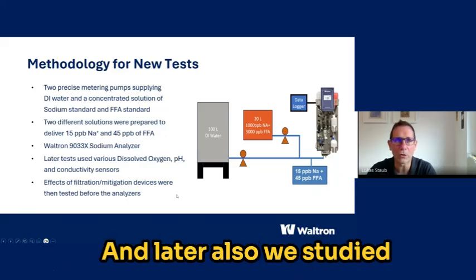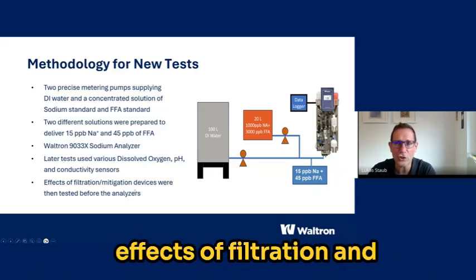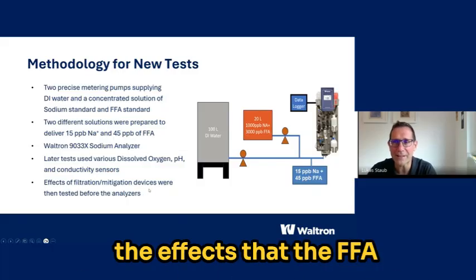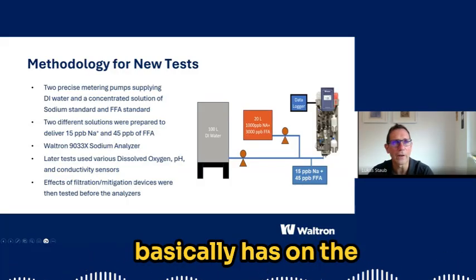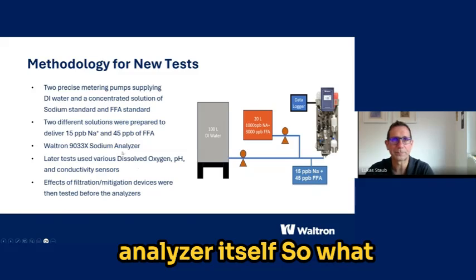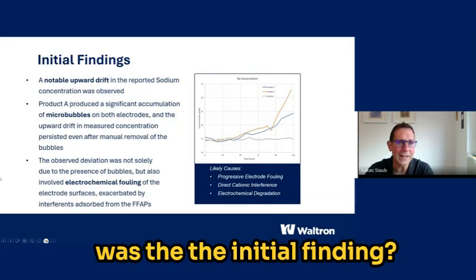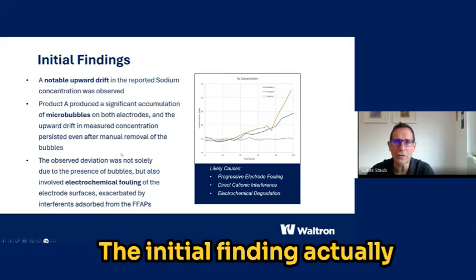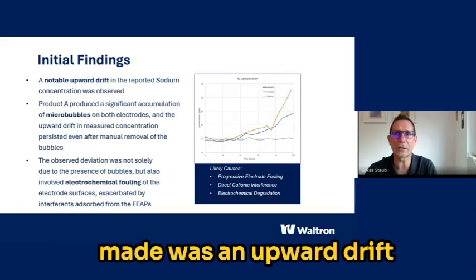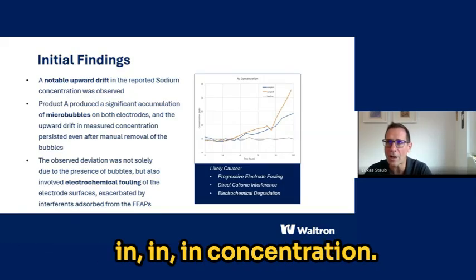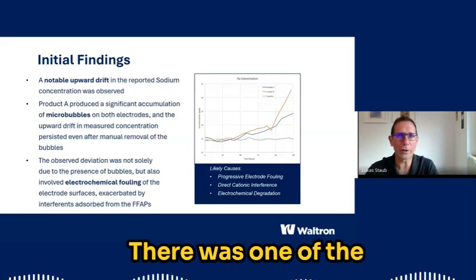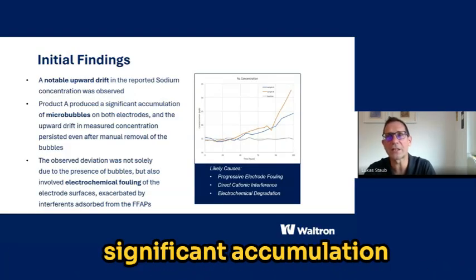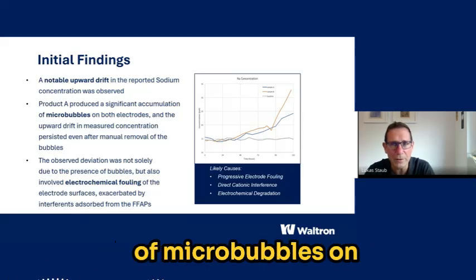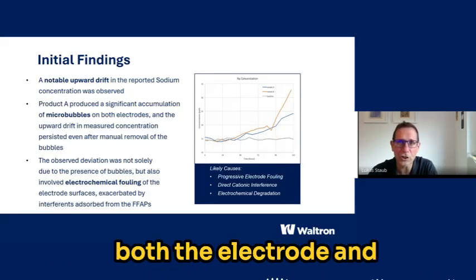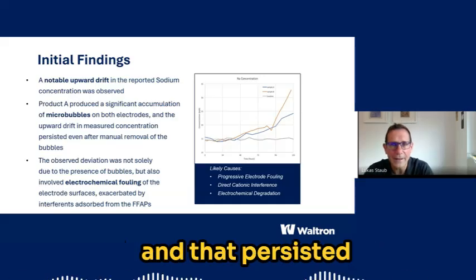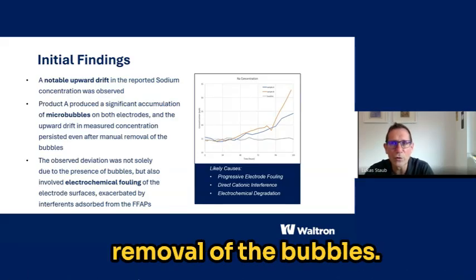And later also we studied effects of filtration and how we can mitigate the effects that the FFA basically has on the analyzer itself. So what was the initial finding? The initial finding of those tests was an upward drift in concentration. One of the products that was tested showed a significant accumulation of microbubbles on both the electrode and the reference electrode. And that persisted even after manual removal of the bubbles.